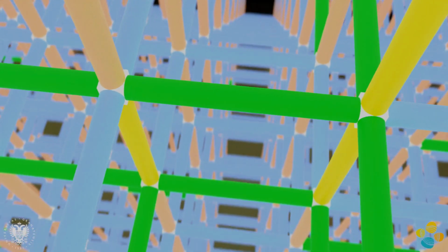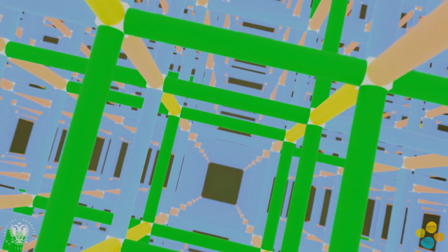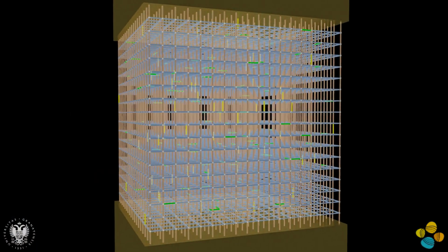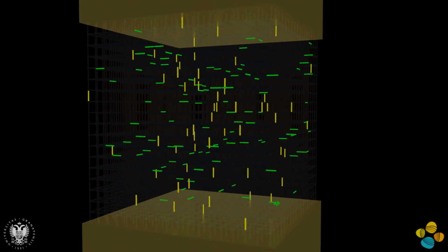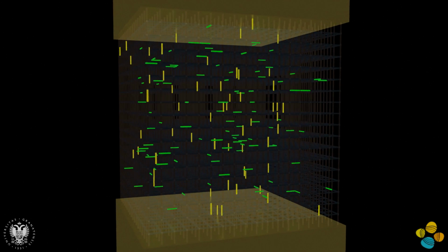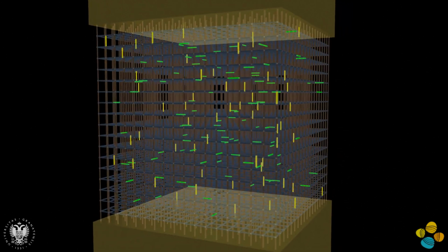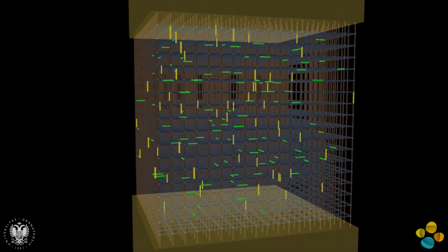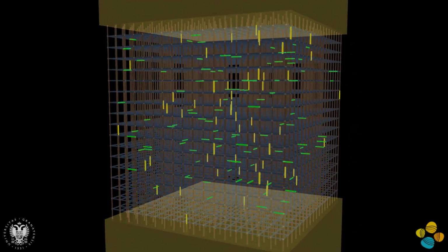We can either choose some resistances to be in the low state randomly or include areas of defects with a high probability of low value resistances. This is a more realistic approach, as these regions are usually found in the dielectric. Depending on the voltage difference on each resistance, the initial high value is switched to a lower value in the forming and set processes. In this manner, the conductive nanofilaments are formed.